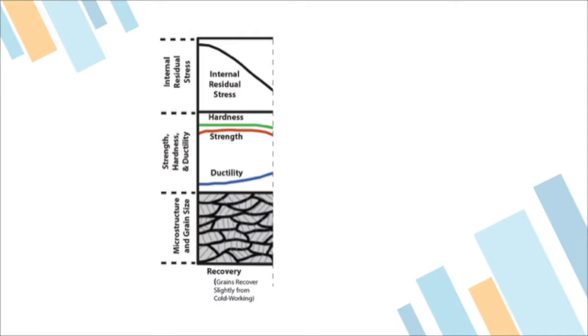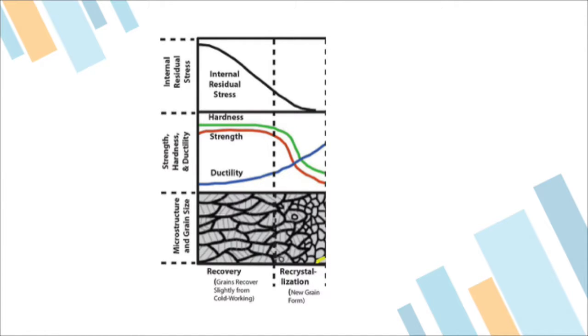Now, finally, we have recrystallization, the step that occurs after recovery. If increased thermal activation is available, so for instance, if the temperature is raised, nucleation and growth of strain-free grains in the deformed matrix will take place. Now this is important. As these grains grow, the dislocations in the matrix are annihilated at the boundaries of the newly formed grains. Strength and hardness decrease considerably, and ductility increases.